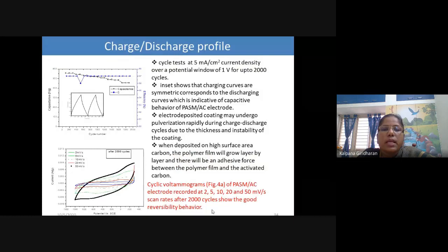This is cycled at 5 milliamp per centimeter square current density with a window of 1 volt, cycled up to 2000 cycles. It was giving good capacitance, and you could see the blue line for carbon. There was some drop near 600 cycles, but otherwise it shows a typical symmetric behavior.